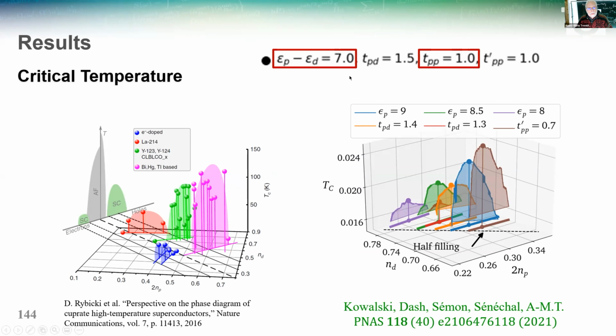The reason we use this model, which turned out to be not that realistic, is because to do continuous time quantum Monte Carlo, you basically have a narrow sweet spot, and this is the sweet spot. On the right is the calculation. If you look at the oxygen hole content, now on this axis, 2NP, and what's plotted here is TC calculated with continuous time quantum Monte Carlo, you see that there's again a correlation between large oxygen hole content and large optimal TC.